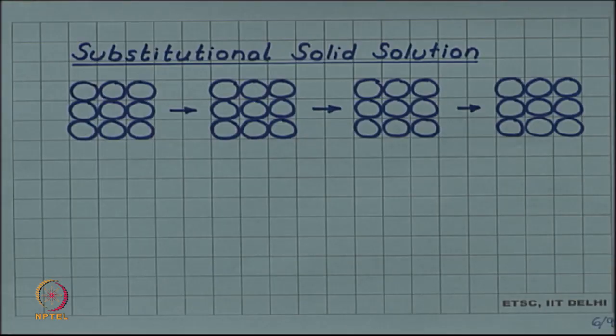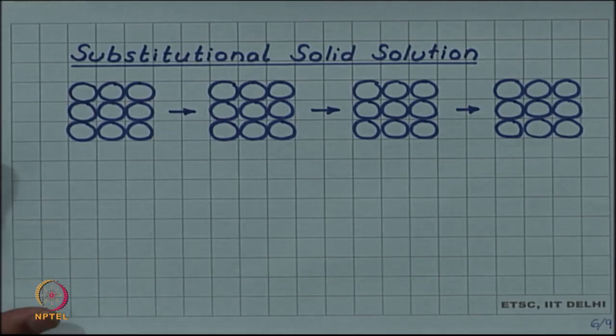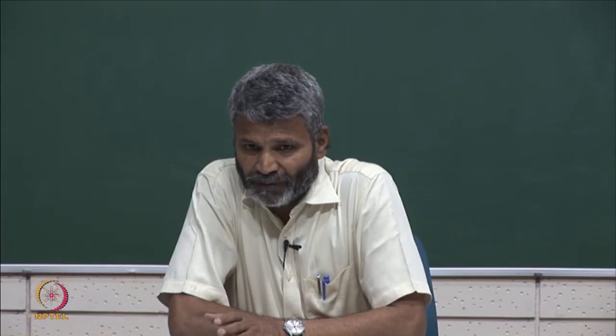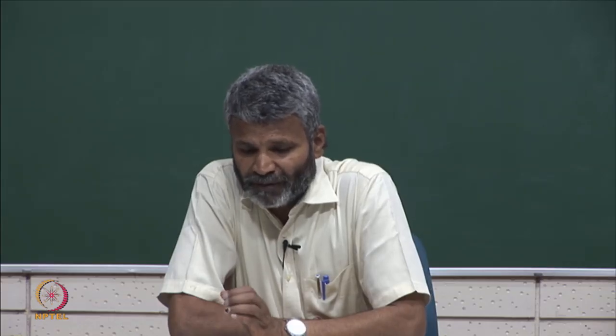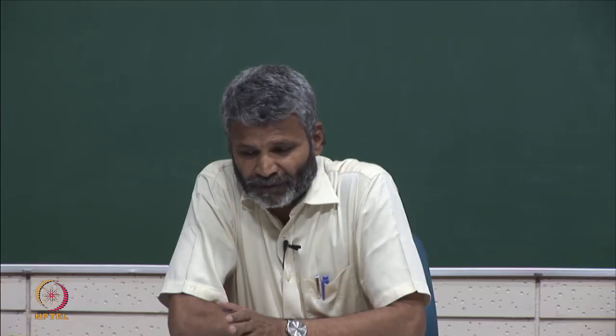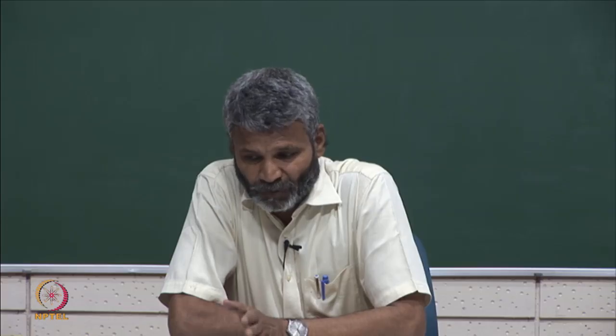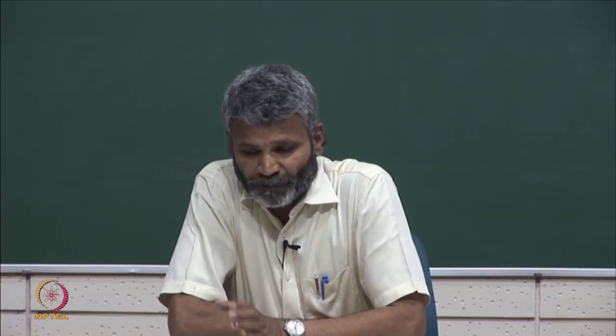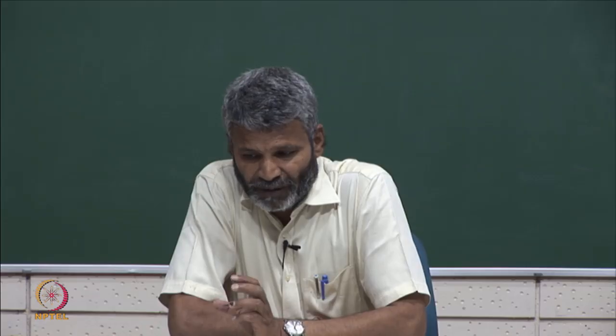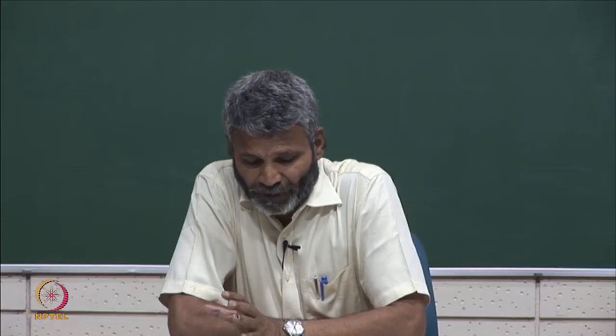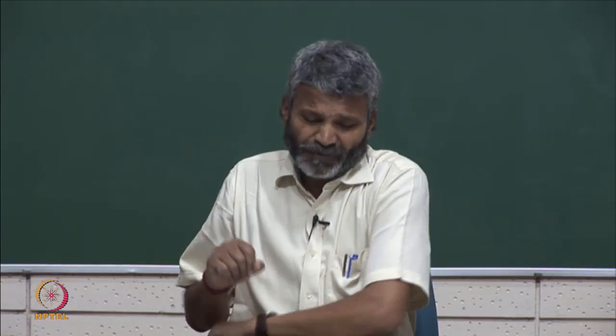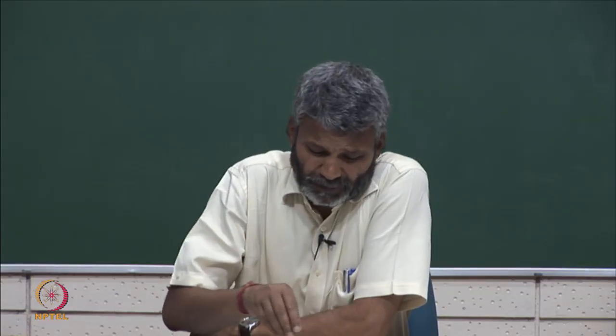Now, let us look at the substitutional solid solution. In the interstitial case we saw that there is a maximum upper geometrical limit which cannot be exceeded, and in reality the real limit may be even less than the geometrical limit, and usually it is much less, as we saw in the case of carbon in iron, because of the misfitting. The atoms do not fit exactly in the void and cause strain. What is the situation in substitutional solution? Let us start with this substitutional solid solution.